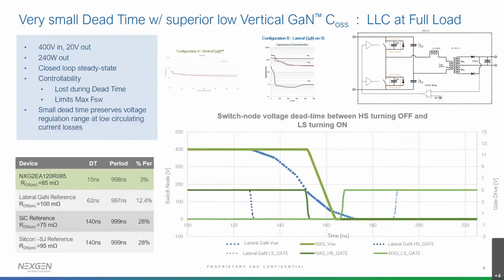The next slide gives a little bit more explanation, but it addresses a topic which may come up: that a device with a very low output capacitance may not be as beneficial in zero voltage switching applications, where the output capacitance is perceived as not very important. But if you look a little bit more in detail into the operation of an LLC, and we have done some studies on that, then you will see that the output capacitance is directly related to the dead time which you have to employ before switching, let's say, from a high side transistor in an LLC configuration to a low side transistor. We have done some simulations based on our device models and compared this with what is known from lateral GaN on silicon devices.